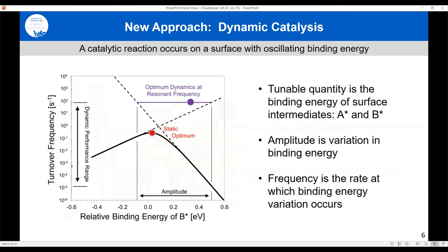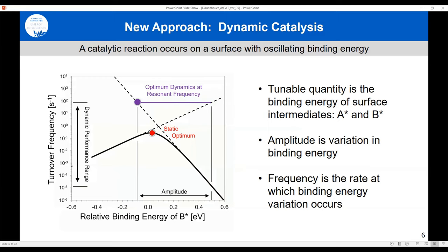In a simple A-to-B reaction: in state one it's favorable to go from A to A* through the transition state to B*; when we oscillate to state two, it's more favorable for desorption. Flipping between these two states is favorable for each of the two rate limitations — surface reaction and desorption. This is like taking each elementary step and extending it above the Sabatier optimum.